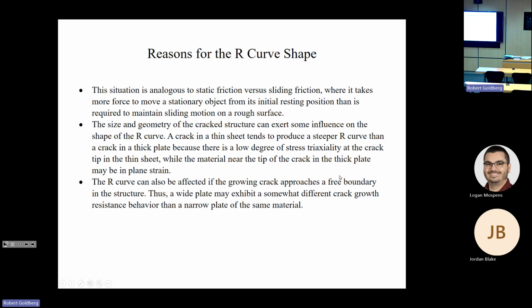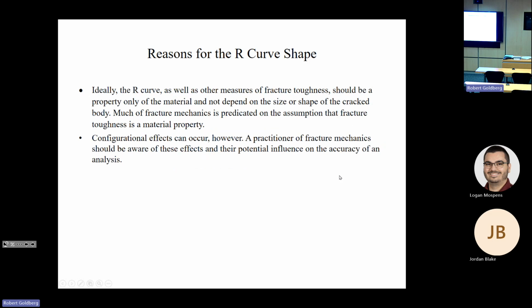And just if this wasn't all complicated enough, the R curve can also be affected as you approach a free boundary. A wide plate may exhibit a somewhat different crack growth resistance than a narrow plate, because when your crack gets near your boundary, all of a sudden you have boundary effects that come into play, and boundaries promote stress concentrations, which is another thing that can lead to the growth of your cracks.